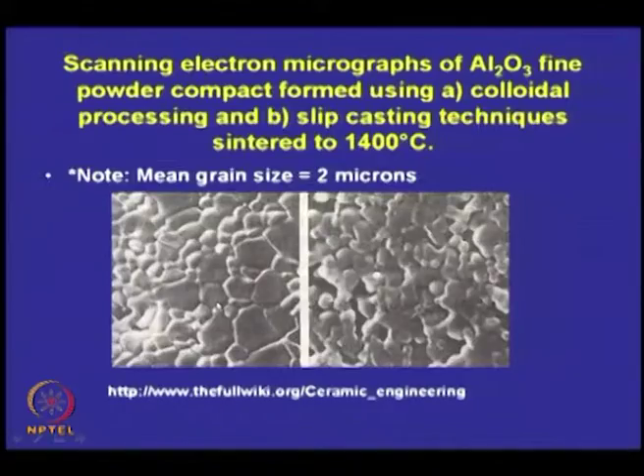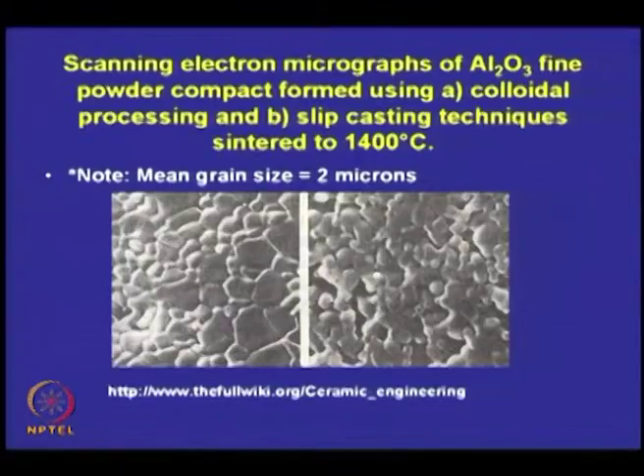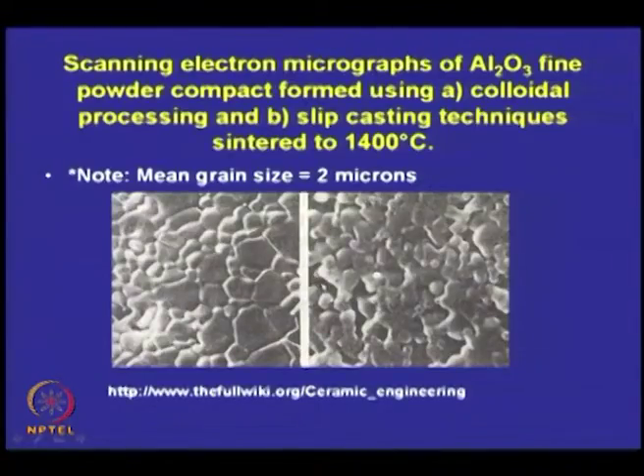If we take this to 1400 degrees centigrade, you will see that the one done by colloidal processing, where the packing was much more uniform, has a very dense microstructure. Whereas the one made by slip casting has a lot of porosity in it. All these dark spots are pores. So grain growth has not occurred over here to the extent it has occurred in this one.